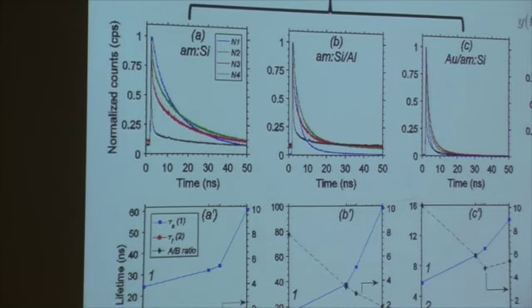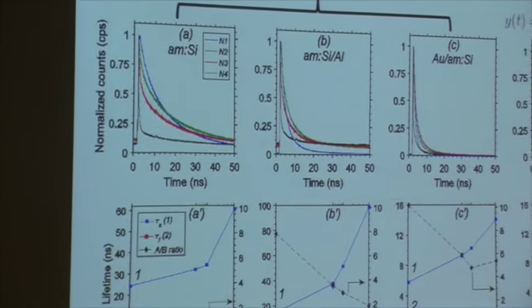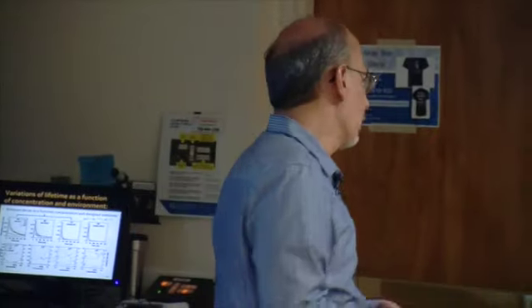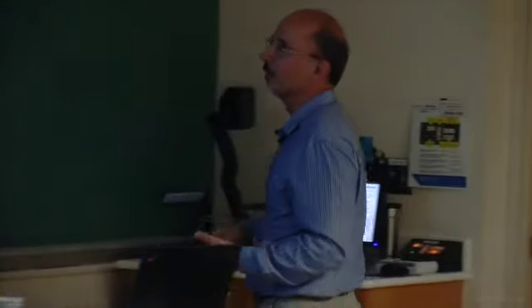Of course, the reason behind that is that if you have an ensemble of quantum dots, before a quantum dot gets trapped into the defects of the silicon, it goes to another quantum dot. And it gives you a better chance to emit light, so you can collect light before you lose the electron hole. But if you make a single quantum dot, instantly when you generate the light, it gives off its energy, because the carrier goes to the substrate, and the light goes off. It is very fast.